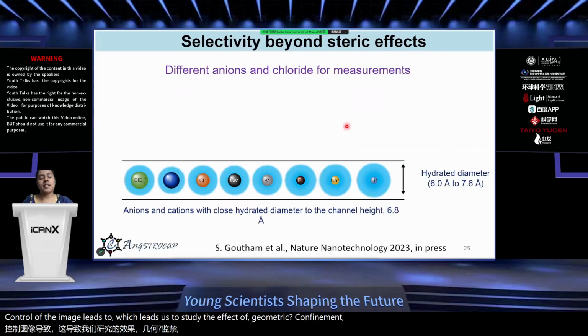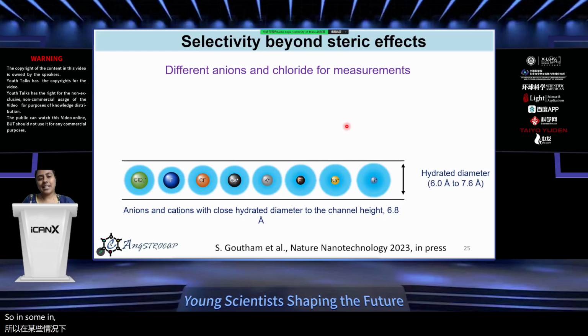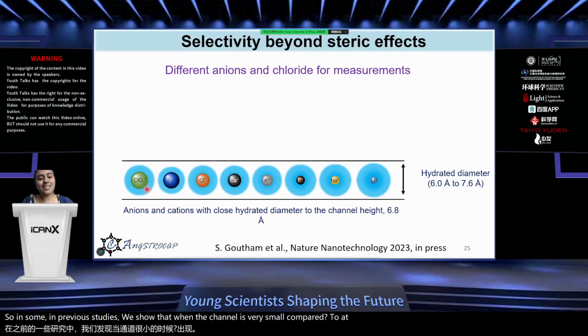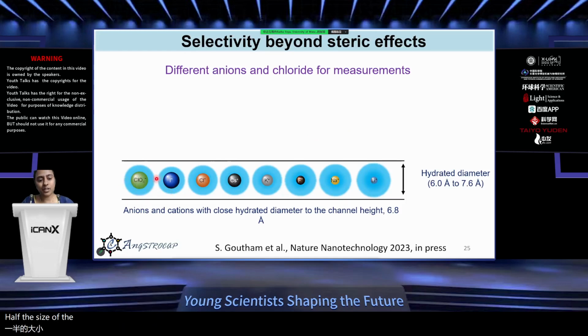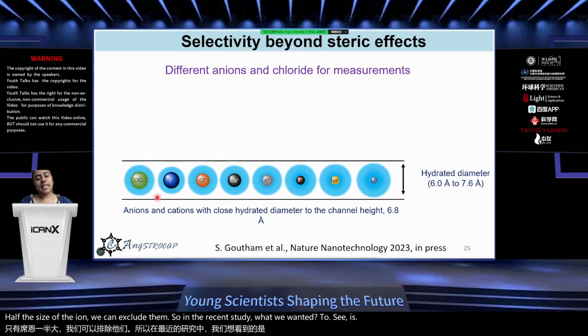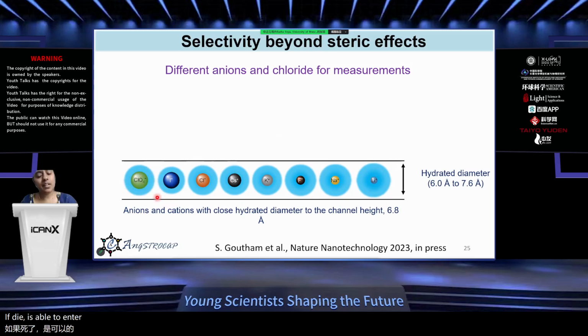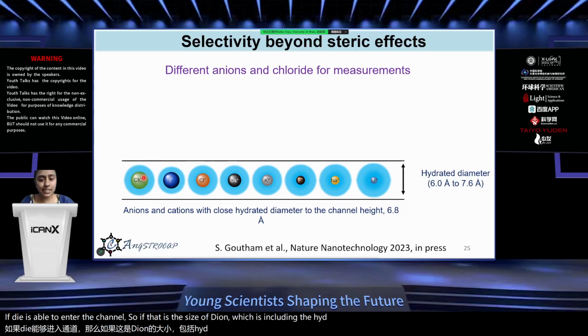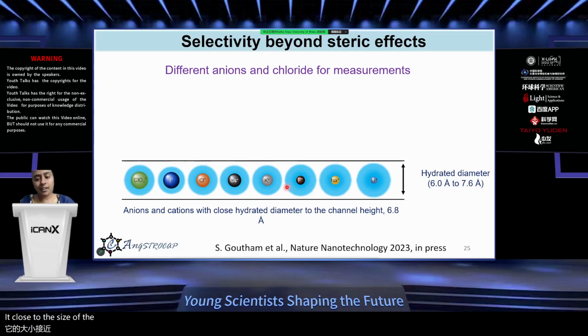So in previous studies, we showed that when the channel is very small compared to at least half the size of the ion, we can exclude them. So in the recent study, what we wanted to see is if the ion is able to enter the channel. That is, the size of the ion, including the hydrated diameter, is close to the size of the channel. Is there any selectivity between the ions?